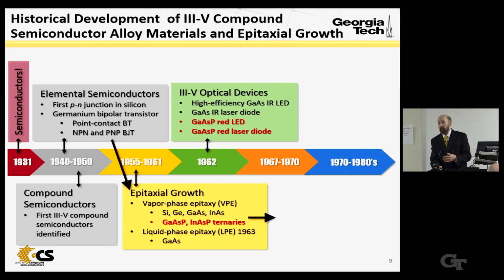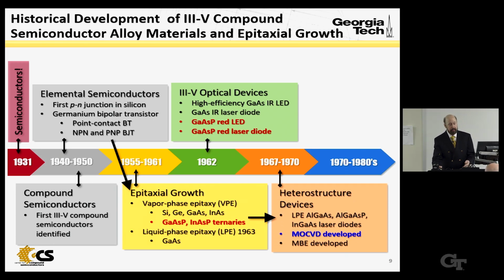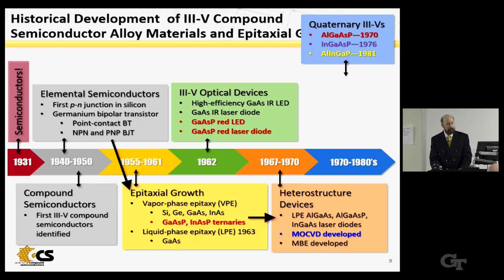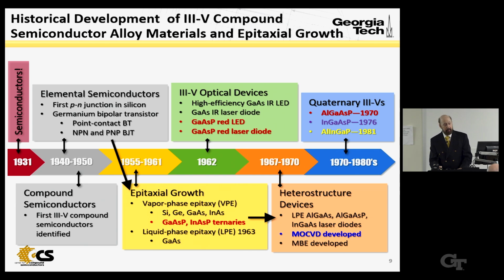The availability of epitaxial growth led to the development of heterostructure devices, in particular LPE of aluminum gallium arsenide and aluminum gallium arsenide phosphide, as I mentioned. InGaAs laser diodes were developed. In 1967, MOCVD was developed, and the same year, roughly, MBE was first described. This led to, as I earlier referred to, the first quaternaries in 1970, aluminum gallium arsenide phosphide, and the first infrared emitting quaternary, indium gallium arsenide phosphide in 1976. In 1981, the first aluminum indium gallium phosphide for red and yellow LEDs.